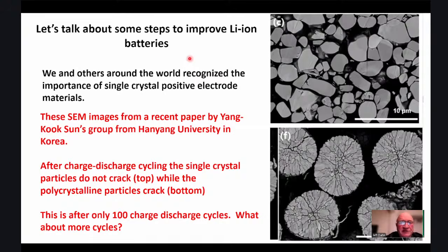So I want to talk about one easy way to improve lithium-ion batteries, and that's to eliminate this microcracking that we've talked about already. The upper image shows a SEM image of so-called single crystal positive electrode materials after 100 charge discharge cycles. And the lower shows an image of the standard NMC particles after 100 charge discharge cycles. Each of these particles in the upper panel is a single crystal. It's made up of one crystallographic orientation. So it just expands and contracts as a whole, and there are no grain boundaries for these microcracks to form along. So it's really incredible.